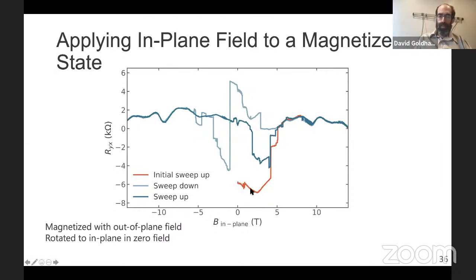And you can see that this big Hall signal disappears at around between 4 and 6 Tesla. And then beyond that, there's just some oscillation in the Hall signal, but it's pretty flat. And then when we get below this 6 Tesla value, we again start to see a Hall signal that's hysteretic. And then when we go in the other direction, again, we come to a state where the Hall signal is not hysteretic. So it looks like there's some trend that at relatively low field, we have at least 2 possible states, and we can flip perhaps somewhat randomly between them. But when we go to high field, there's some new state, and we don't yet know what it is, but I think there's some effort to understand what's happening to the spin at those high fields.